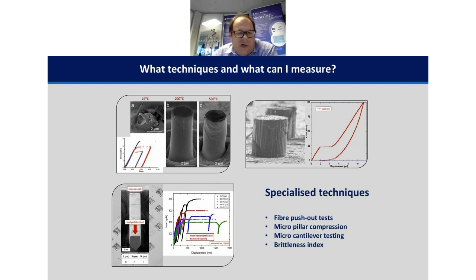Micropillar compression similarly allows us to interrogate a small volume of material, and because we're working with a fixed volume of material, this is rather like a nanoscale tensile or compression type test, where we can convert our load and displacement data directly to stress strain very easily. We can also work with materials other than bulk and coatings, including composite materials. Here we're looking at debonding forces in fiber reinforced composite materials, where we use a flat indenter to push fibers out. Coatings are a very important part of what we do, but we can also work with a wide range of other material types.